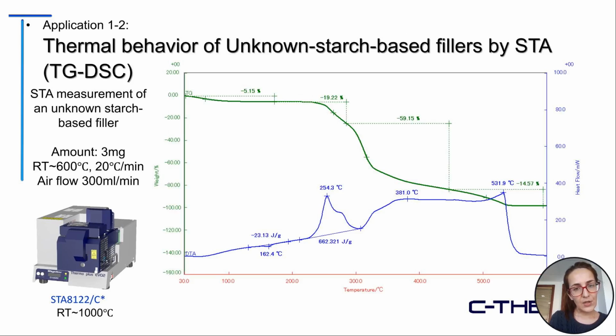The unknown starch-based filler followed the same trend, both for the TGA and DTA. We have four mass losses in the TGA curve, and also a small endothermic peak at 162, which is followed by an exothermic peak at 254, and a wide exothermic peak at 381, which is related to the combustion of the unknown starch-based filler.